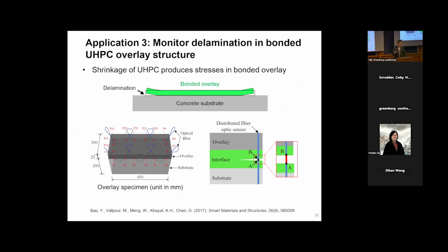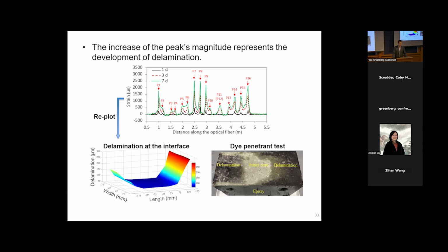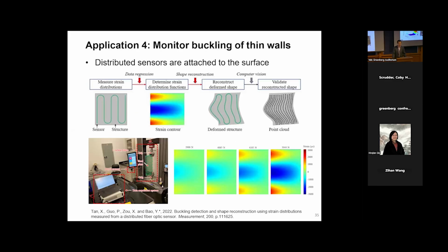Another application is that we can use this type of sensor technology to monitor interface debonding or delamination. For example, we apply ultra high performance concrete to repair a damaged concrete slab. We can cast a layer of ultra high performance concrete, but at the interface, because of the different shrinkage behavior, there will be debonding. Currently it's very hard to monitor this debonding behavior, so we use the distributed sensor to monitor this. Based on our monitoring results, my collaborator was able to further improve the design of the material so that we can minimize the interfacial delamination.